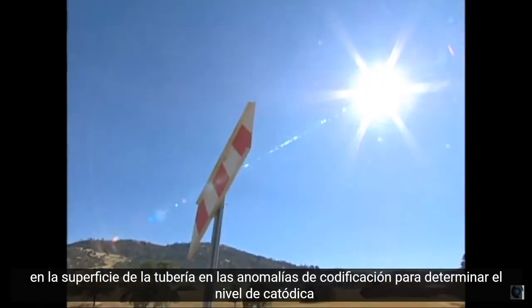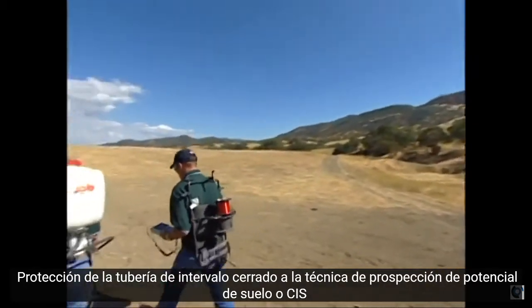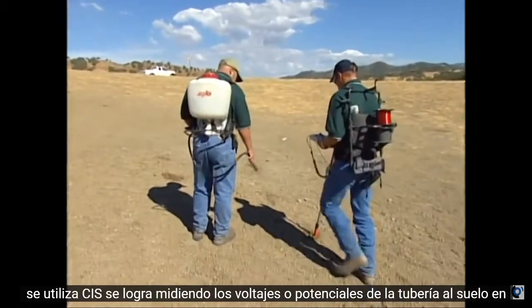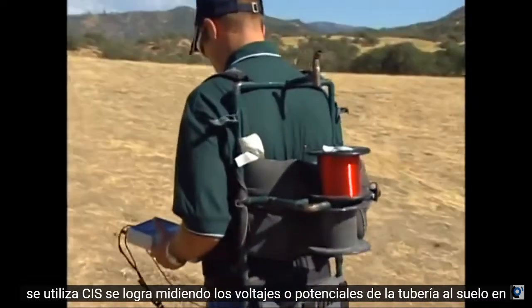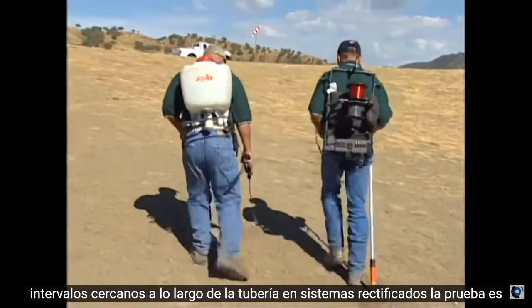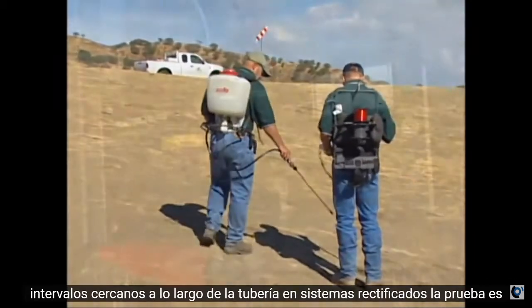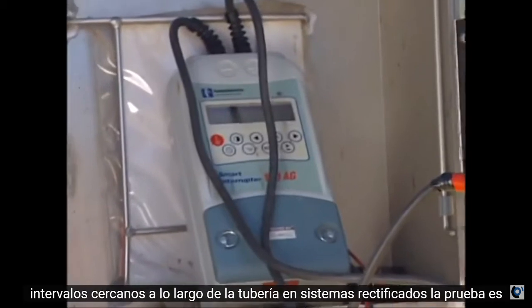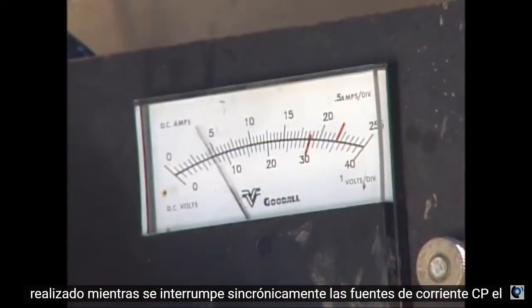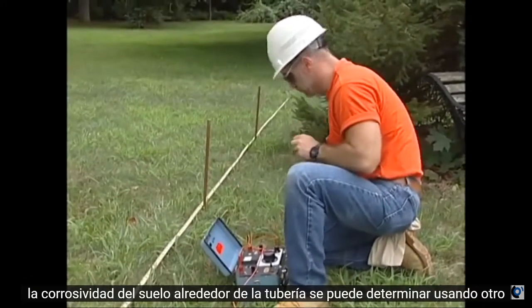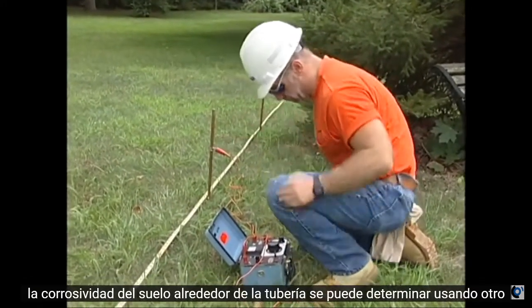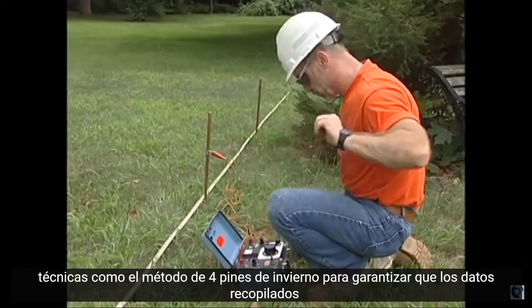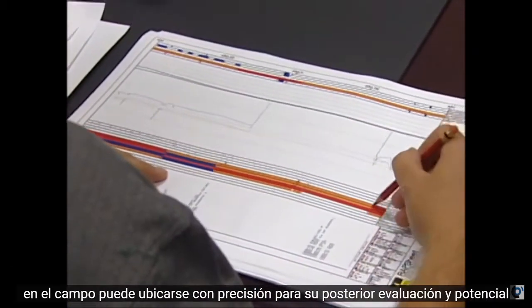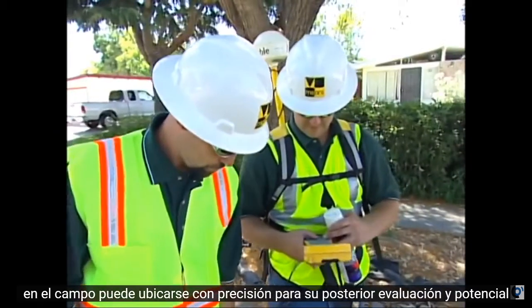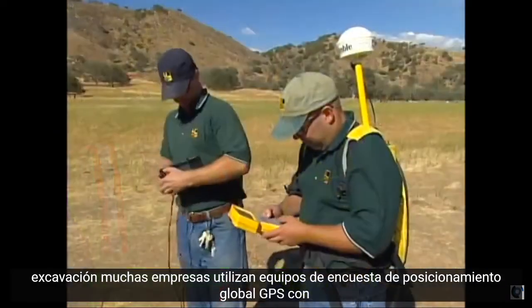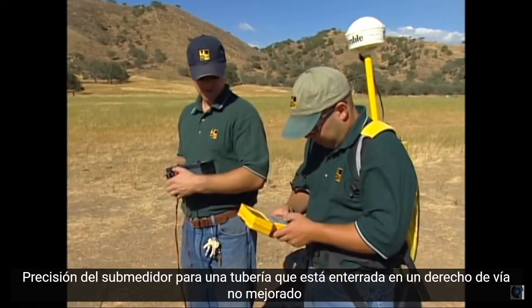To determine the level of cathodic protection, the Close Interval Pipe-to-Soil Potential Survey Technique, or CIS, is used. CIS is accomplished by measuring pipe-to-soil voltages, or potentials, at close intervals along the pipeline. On rectified systems, the testing is performed while synchronously interrupting the CP current sources. The corrosivity of the soil around the pipeline can be determined using other techniques, such as the Wenner four-pin method. To ensure that the data collected in the field can be accurately located for subsequent evaluation and potential excavation, many companies use Global Positioning Survey equipment, GPS, with sub-meter accuracy.